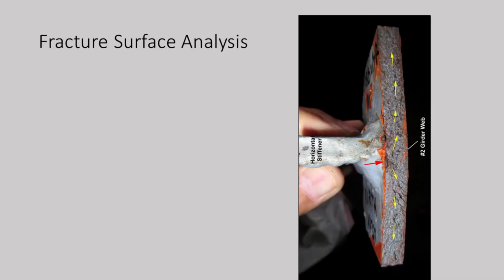And a lot of times when you have these brittle fractures, you generate this chevron pattern, okay? And the chevron, there'll be concentric chevrons, and they'll point back to the source of the failure. And in this case, he put some yellow showing the direction of crack propagation, but the chevrons were pointing in the opposite direction. So what we can see here is basically the crack started at this point where this red arrow is and ran up, and it ran down concurrently.